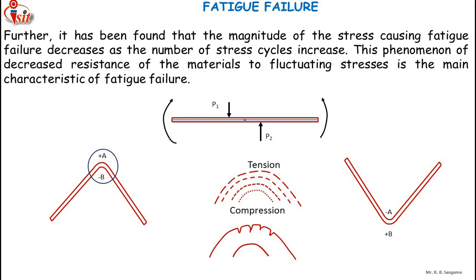These regions are most likely to experience stress concentration. The crack spreads due to fluctuating stresses until the cross-section is so reduced that the remaining portion undergoes sudden fracture. There are two distinct fracture areas: a region of slow crack growth with a fine fibrous appearance, and a region of sudden fracture with a coarse granular appearance. Under static load, sufficient plastic deformation gives advance warning, but fatigue cracks are not visible until they reach the surface, by which time failure has already occurred.